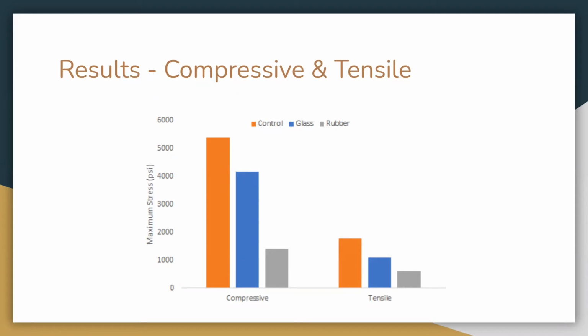The tensile test showed a similar pattern. The glass was lower than the control, and the rubber was even lower than the glass. Looking at the rubber sample's average density and compressive strength, we can see that its low density came at the cost of its strength.